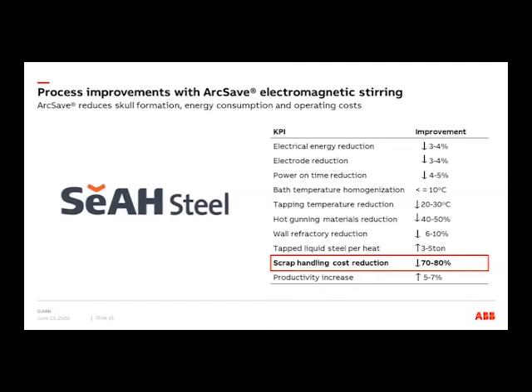Other savings worth mentioning was, of course, the hot gunning materials, which was reduced by 40 to 50%. And this can be explained by that we had less superheating on the surface or on the meniscus, and therefore we had less slag attack in the slag line. Another saving was similar to Avesta, for example, the electrical energy reduction, 3 to 4%, and power on time reduction, 4 to 5%.